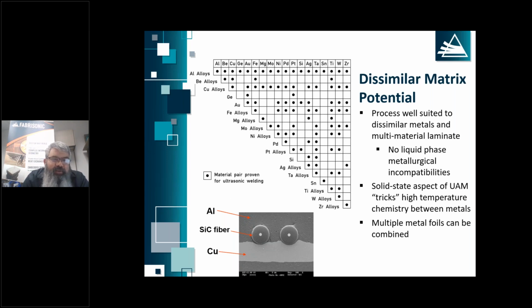Tantalum onto steel, tantalum onto aluminum, tantalum onto copper. We've recently been doing a lot of work with zirconium. We've done tungsten to steel, tantalum to steel, zirconium to steel, pretty much every kind of nickel alloys to steel. You get the picture. There's a wide array of different dissimilar metal combinations that we can make in order to create a custom material. The few items that really don't work well in an ultrasonic weld are things that are self-lubricating. So let's say you have a cast aluminum, let's say that's maybe 5 or 6% silicon by volume or by weight.